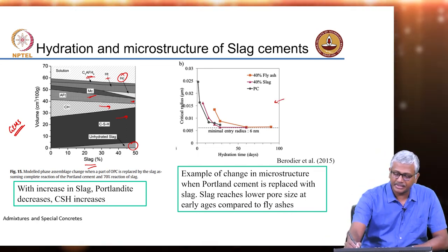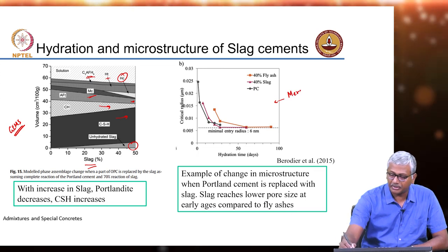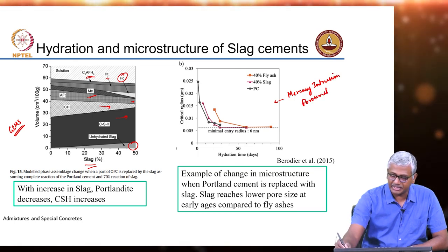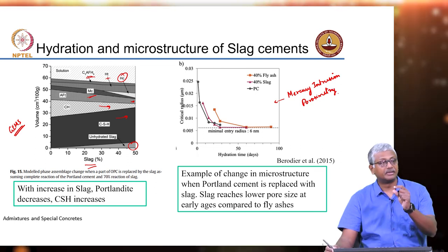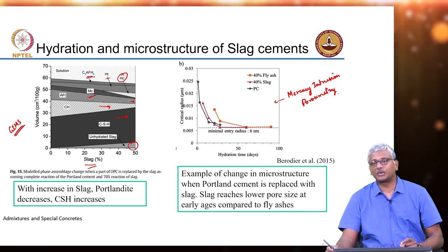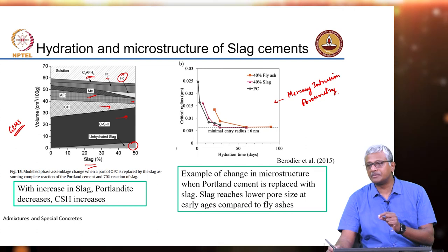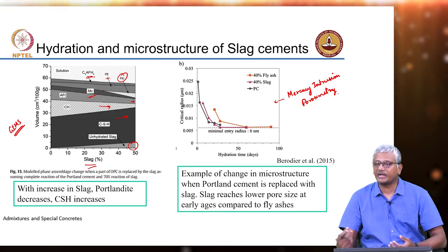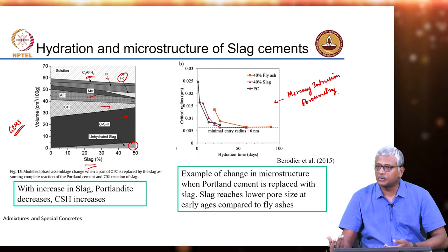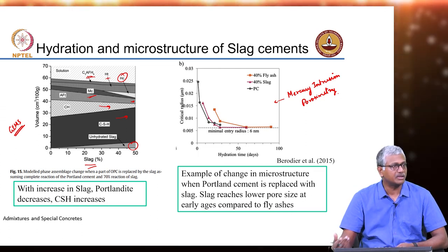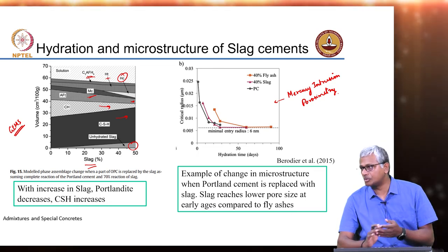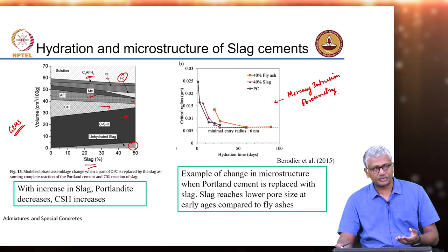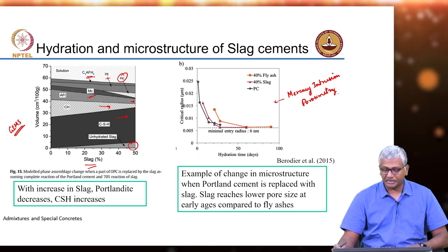This is a result from mercury intrusion porosimetry. In this experiment, you take a sample of hardened cement paste and subject it to continuously increasing pressures of mercury. You immerse it in mercury and pressurize it to get mercury into the pores. Mercury is chosen because it does not wet the surface — it is a non-wetting liquid with an obtuse contact angle. So mercury is able to penetrate the pores without getting stuck to them. The higher the pressure, the smaller the diameter of the pores that the mercury will penetrate. So you can actually get a range of pore sizes from the experiment.